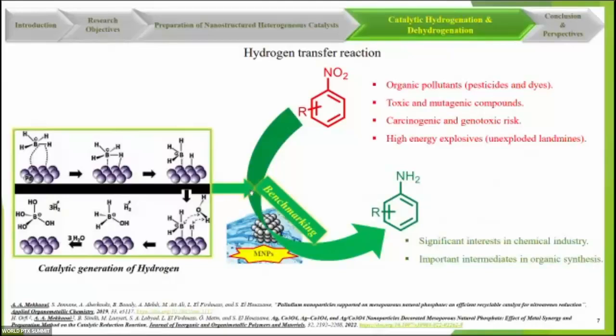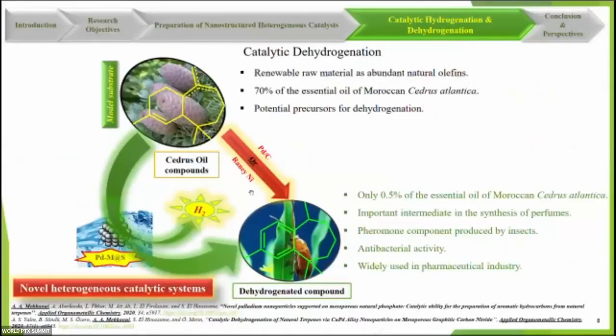For the catalytic applications, we first studied the hydrogen transfer reaction, and the capacity of the developed nanocatalytic systems in the catalytic generation of hydrogen from borohydride. We also ran a benchmark catalyst test, well known for testing nanoparticles and their catalytic activity: the reduction of nitro compounds, which are considered organic pollutants with harmful effects on nature and soil, and to prepare chemical products of significant industrial interest such as amino compounds, important intermediates in organic synthesis.